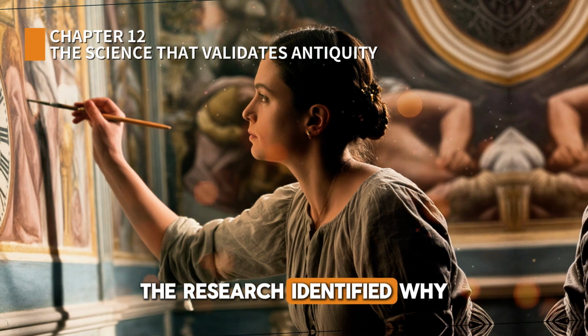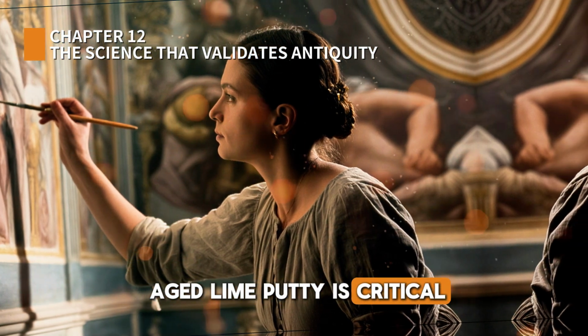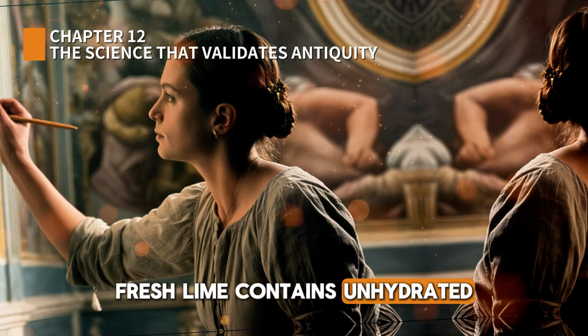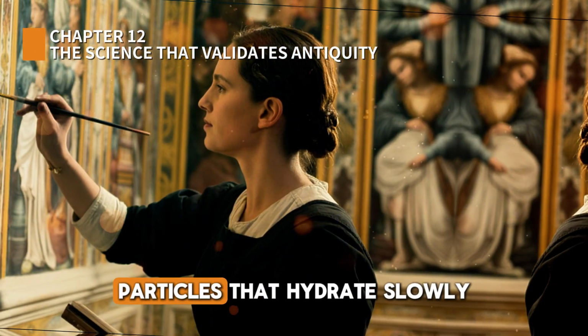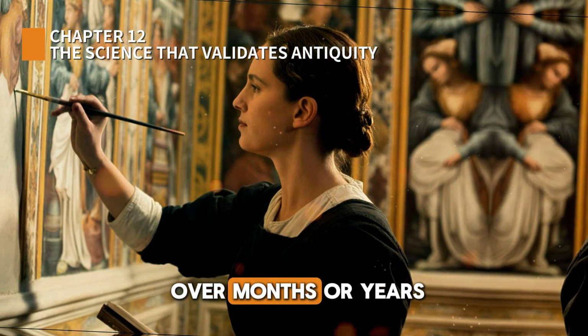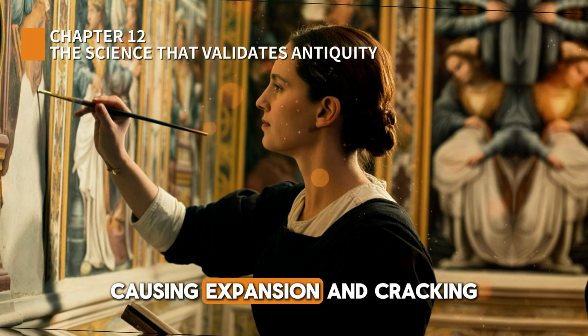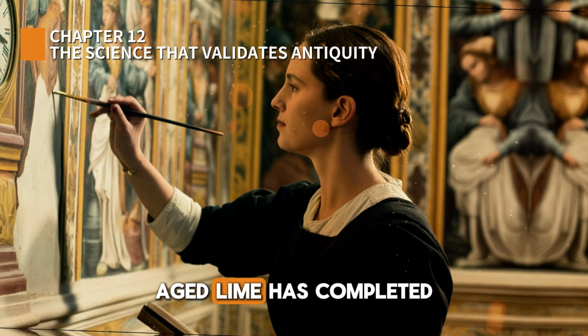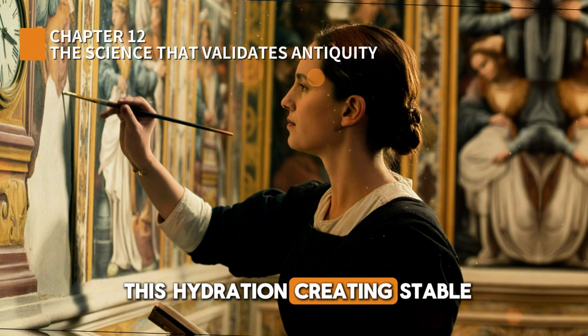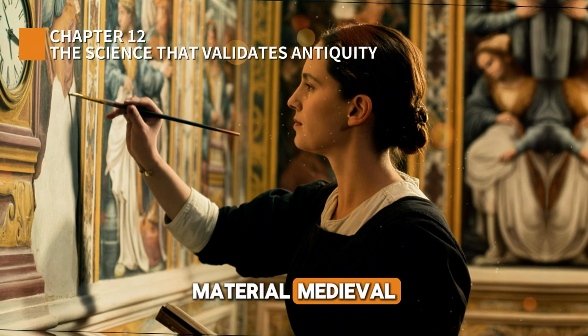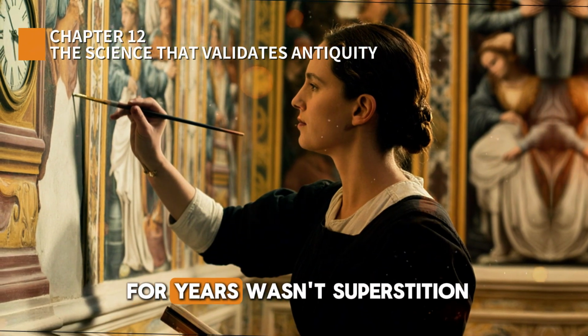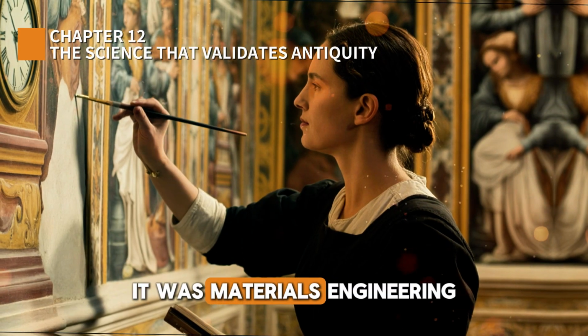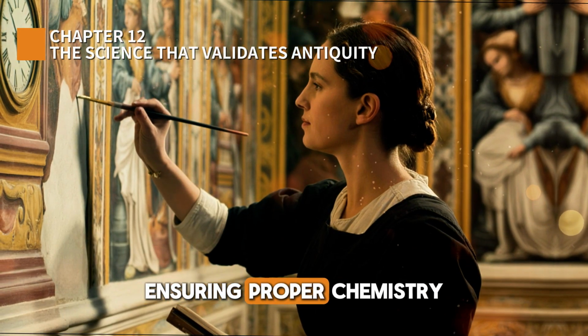The research identified why aged lime putty is critical. Fresh lime contains unhydrated calcium oxide particles that hydrate slowly over months or years, causing expansion and cracking. Aged lime has completed this hydration, creating stable material. Medieval practice of aging lime for years wasn't superstition. It was materials engineering, ensuring proper chemistry.